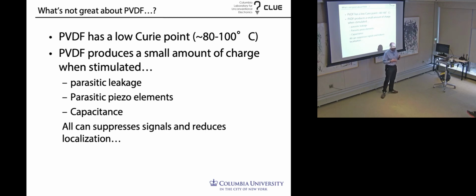The second issue, which I also mentioned before, is that PVDF, when it's stimulated, doesn't produce an enormous amount of charge. And normally, that might not seem like such a problem, but if we want to make an array or something big, what that means is that we only have a little bit of charge to work with and to overcome all of the parasitics, and there's lots of parasitics. We have parasitic capacitances, but in an array, we'll also have parasitic piezoelectric elements, which is really problematic. And so we need to figure out how to get around this.